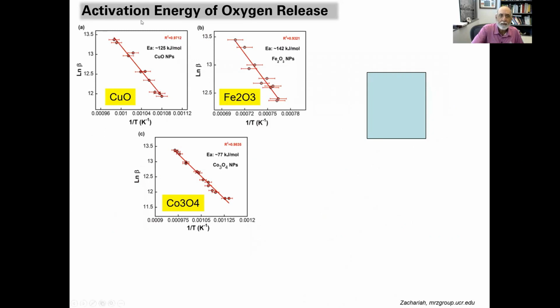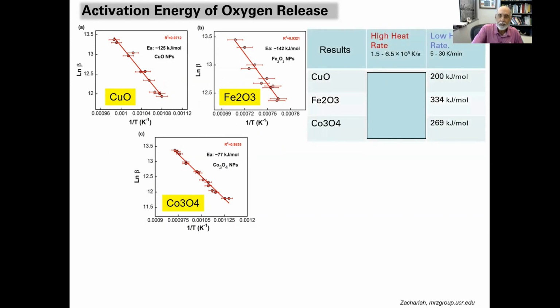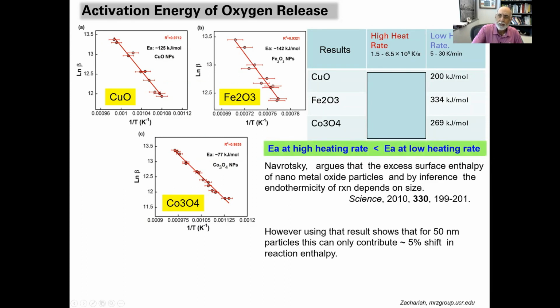So we can extract, for example, the activation energy for oxygen release using these experiments. And these are examples of that, those Arrhenius plots. I'll just summarize the data for you. So here is what happens when you do things at slow heating rates, 5 to 30 Kelvin per minute, where you're sort of passing through thermodynamic phases. This is the kind of activation energies one measures. But at high heating rates, you see the activation energies are considerably lower. So at high heating rates, you're really not probing bond-breaking reactions quite as much as probably you are looking at mass transfer limits in the rate at which oxygen is being liberated. And we need to think about how that oxygen transport is really occurring inside an oxidizer.